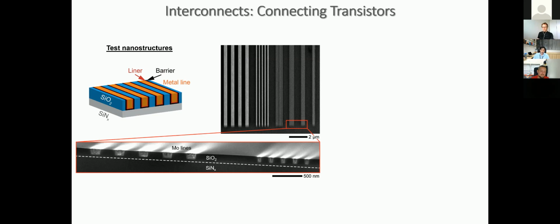So this is something you want to do going into the future. And also, how do we etch them? How do we process them? The surfaces of these things have to be extremely uniform. If there is roughness on the surface, you're going to increase the resistivity due to surface scattering. So you have to be very careful when you etch and when you anneal them, right?